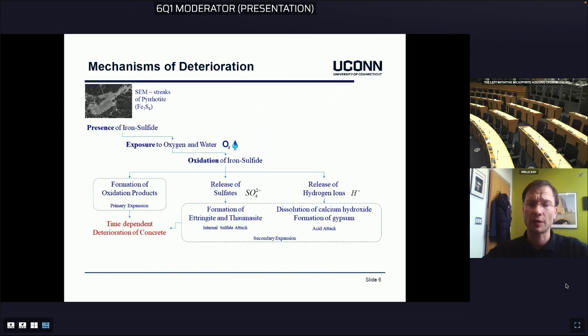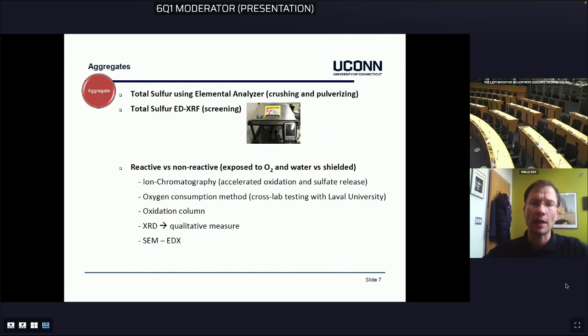Next slide, please. So if we look at the aggregates only, and Benoit has already focused on this detail, like how to evaluate whether those aggregates are suitable for the concrete or not, we would also like to use the elemental analyzer. The aggregates would be sampled, crushed, pulverized, and then the total sulfur amount would be tested. A handheld screening tool, an EDXRF, can be used if you are in a quarry and want a quick evaluation of the total amount of sulfur, to have an indication of whether we have issues with pyrrhotite or other pyrites. This is a good tool as well.